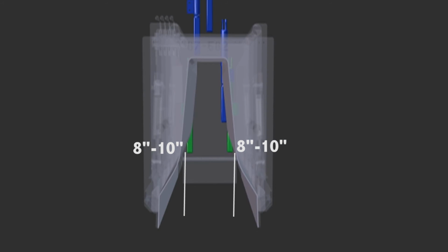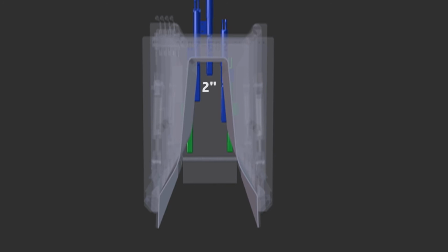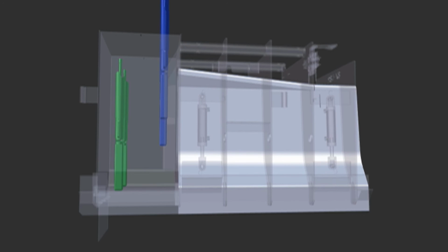Depending on the height of the wall, several more could be placed on the sides. These should be midway down, mounted in the back of the hopper. A vibrator is needed up high to fill the mold and give a slick finish on top. This one will be the traditional 2 inches into the finished wall. These vibrators will be mounted on the back side of the hopper.